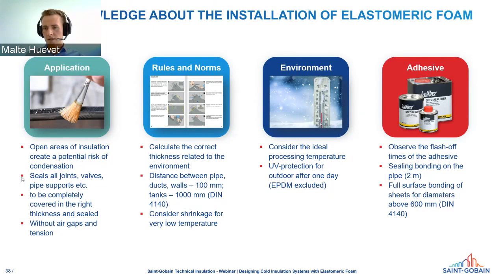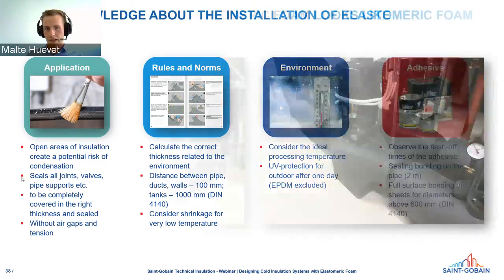Then also the sealing bonding needs to be made on the pipe every 2 meters. That's especially regarding some damage to the insulation. When a section gets damaged, then the insulation just for the 2 meter part will get wet under the insulation, because of course if there is a ripped off part of the insulation, then there is no insulation anymore and condensation will start to form. But all the other parts are completely safe. Also, we need to apply a full surface bonding for diameters above 600 millimeter.